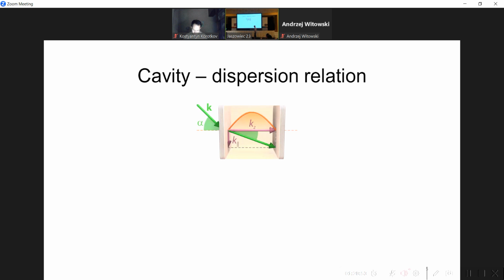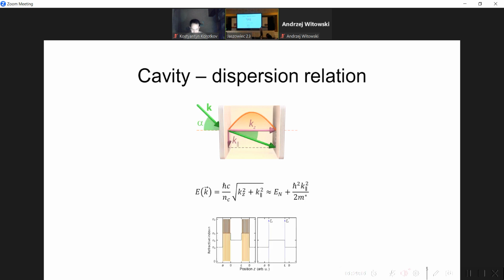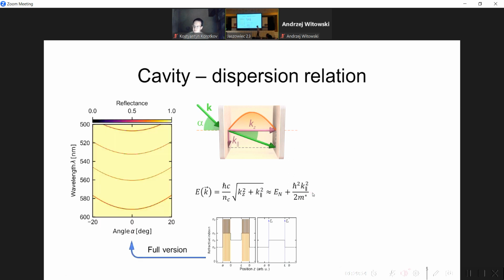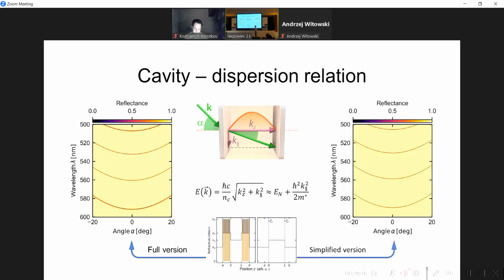But in normal case, we observe many incident angles, and from the previous talk, you know that in this case we get a parabolic dispersion relation with a constant term proportional to mode number and a term proportional to k parallel squared. Now, using the transfer matrix method for the full version of our cavity and the simplified version, we can generate a very similar picture.